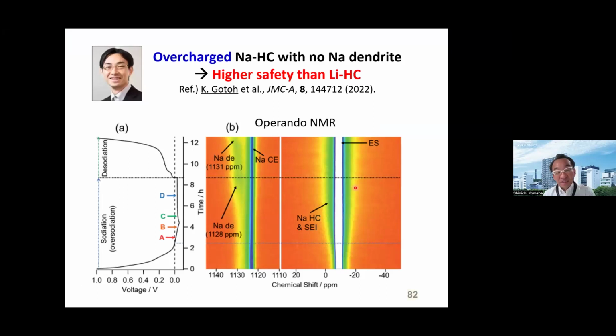Next, our concern is safety. My collaborator, Professor Kazuma Goto, checked the sodium deposition property by operando NMR for the hard carbon sodium half cell. Compared to the lithium hard carbon system, as you can see here, this one shows charge and overcharge of the hard carbon electrode, points A, B, C, and D. Dendrite formation can start from point D.